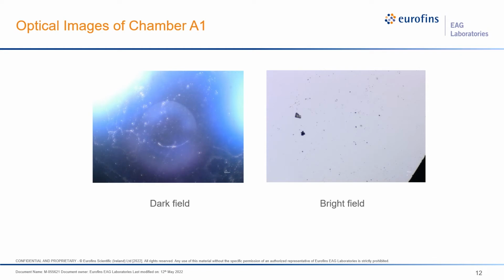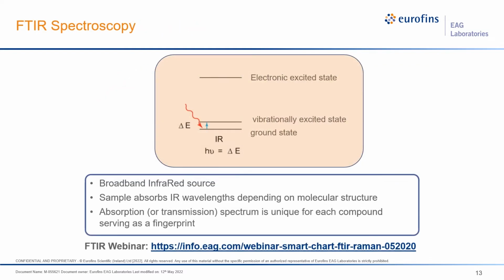So let's look at some images. These are the images that we acquired from one of the chambers from Lab A1, and you can see that this is the same location on the wafer. If you're using a dark field image, you get a very different kind of optical image than a bright field. With the dark field, you can see residues a little bit better. And with the bright field, you can see particles and fibers better.